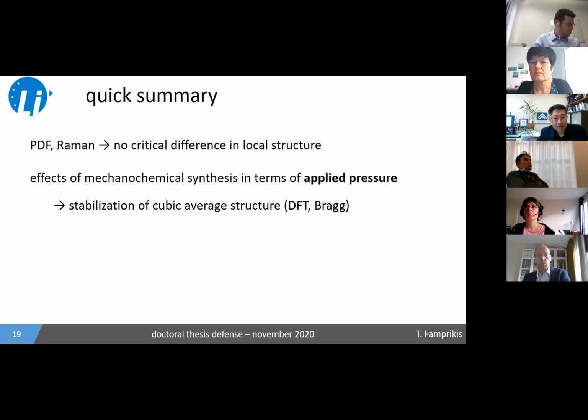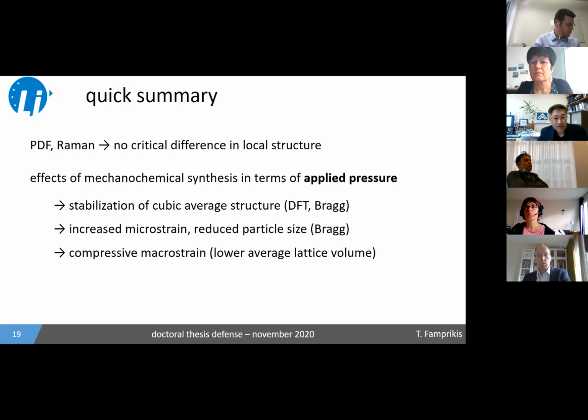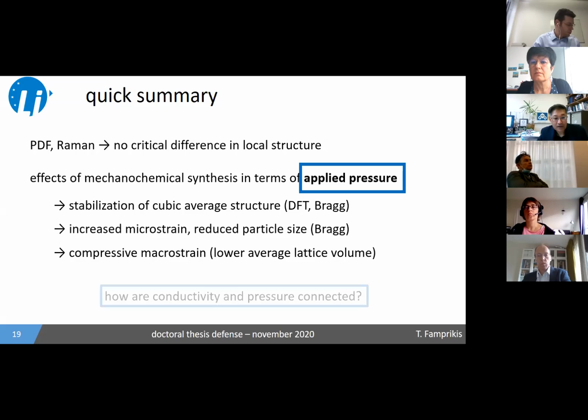So we have a stabilization of the cubic average structure. We have increased microstrain, reduced particle size, and we have some compressive macrostrain, that is a lower average lattice volume upon mechanochemical synthesis. So since something is happening in terms of pressure, the next somehow logical step was, how can we link the conductivity difference that we observe to pressure?